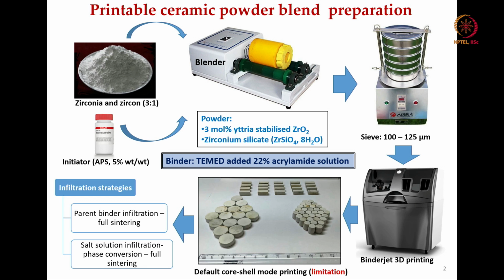Thereafter, as the post binder jet 3D printing treatment, we have used strategies like infiltration. And what is this infiltration? The binder that we used at the binder jet 3D printing stage, the same binder we try to infiltrate into the 3D printed structure, followed by sintering. Another approach we have used is salt solution infiltration, where a zirconium silicate salt solution is infiltrated into the 3D printed structure, and then it goes to full phase conversion during the sintering process.